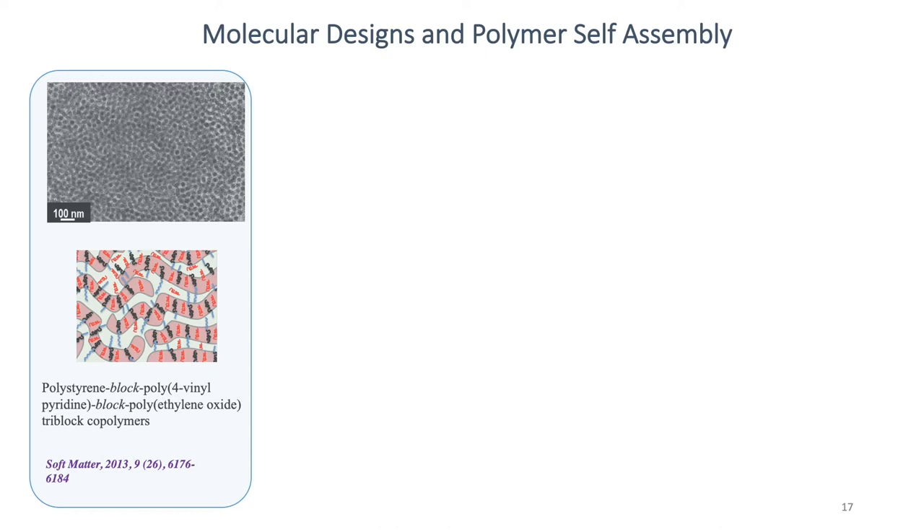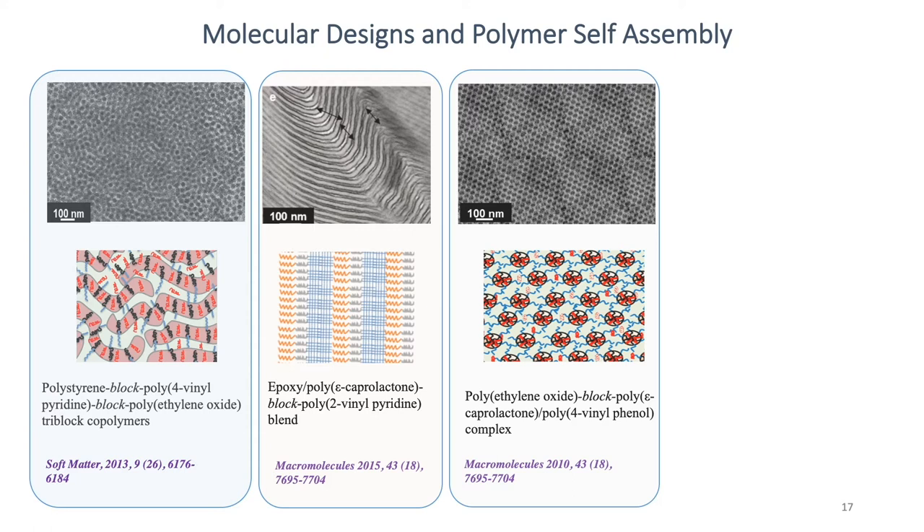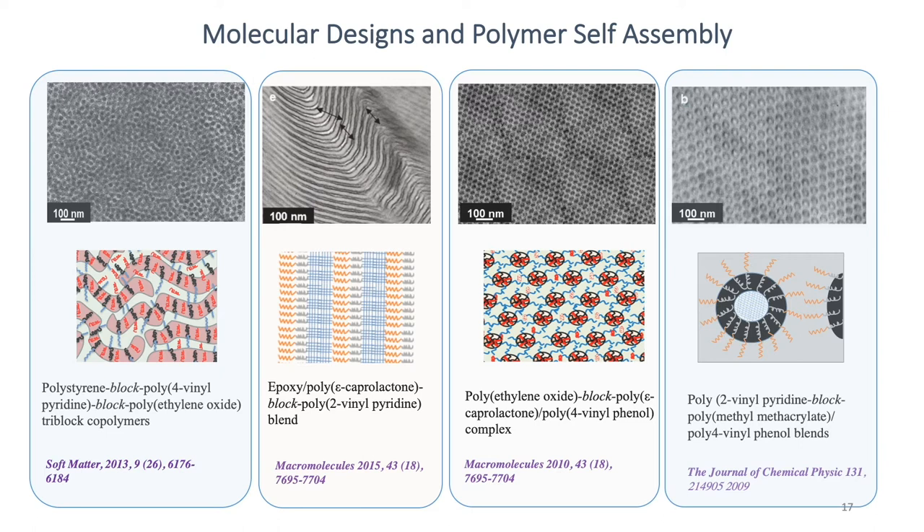We created rod-like features with hexagonal patterns from a tri-block polymer where the polymer has three different chains, and also formed an ordered lamella structure. The orange and blue colors denote the organization of polymer chains. We show hexagonal arrays of nanostructures with size around 30 nanometers, using double crystalline block polymers mixed with a homopolymer system, and hexagonal cylindrical arrays of polymer chains. In summary, we have created various nanostructures both in solution and in solid stage, formed by combining block polymers with other polymers. We can make long-range ordered nanostructures by carefully choosing the polymers, changing their chain length, molecular weight and the composition of each block.